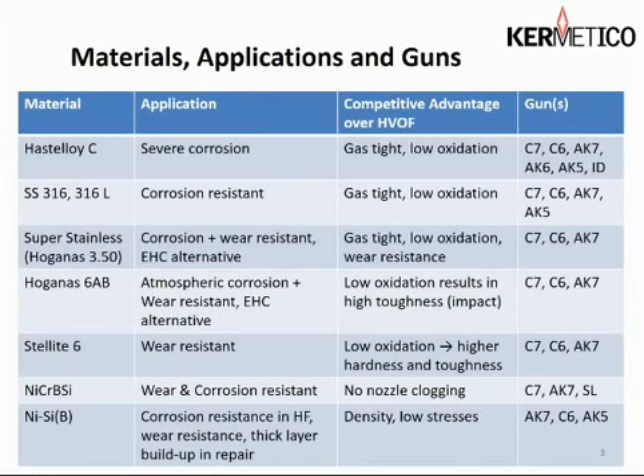Super stainless, or Hoganas 3.50, is a corrosion and wear resistant material that falls in the 52 to 55 Rockwell C range, and it is also gas tight, very low oxidation in the as-sprayed coating, and it is very wear resistant as metal coatings go. And as you can see, we only use our larger guns to spray that so far.